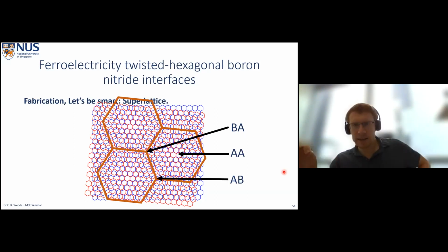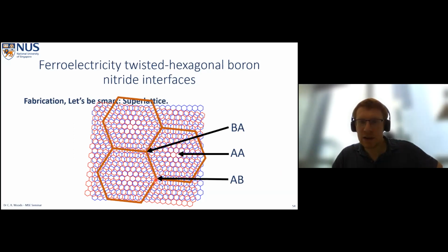And within these larger super lattices, we can see each different type of stacking. So we can see in the middle here, we have AA stacking. And in each of these vertexes, we would have, say, BA stacking here and AB stacking here. So we can be a bit smart about how we approach this. And if we just have a little twist angle between our boron nitrides, we can look at the behavior of BA, AA, and AB all within the same sample.